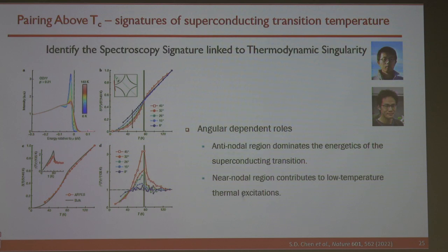We start out with these spectra at a low temperature. We do this cycling of temperature, and we go back to the original temperature and show the spectra after the entire thermal cycle were identical. It's extremely important, otherwise you're not going to get it.